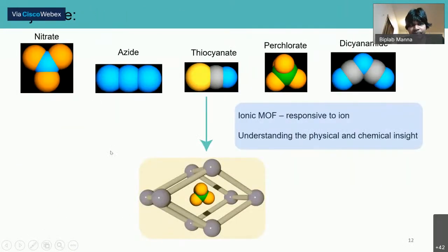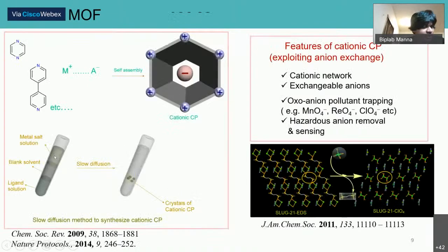In this slide, I explained the detailed technique. This blank solvent layer is very necessary because otherwise the metal salt solution will come down so fast that it will form a precipitate. As we need to have a crystal structure, there is a big gap between the other solvents. At the same time, we checked the miscibility of this solvent as well, because it should be moderately miscible with the benzene as well. Yes. So this is a three solvent system rather than the two we usually use for slow diffusion, but you are using three here to make it slower, right? Yes.